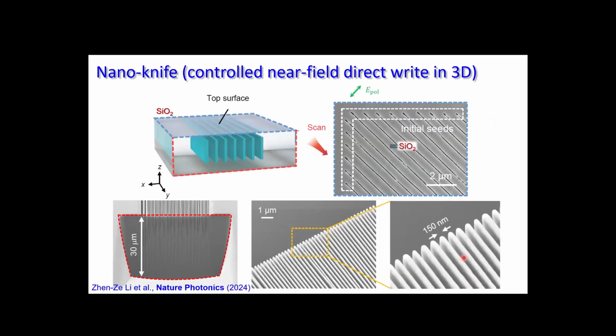So then, a real example, can we use this to modify material in 3D with nanoscale precision? This was silica exposed with a femtosecond Bessel beam, slightly below the surface. Surface is never damaged, so that's why you can write structures inside, and modification is not changing your energy delivery to those slices inside. Then the sample was polished and etched in the etchant to remove modified regions. And this is what you see.